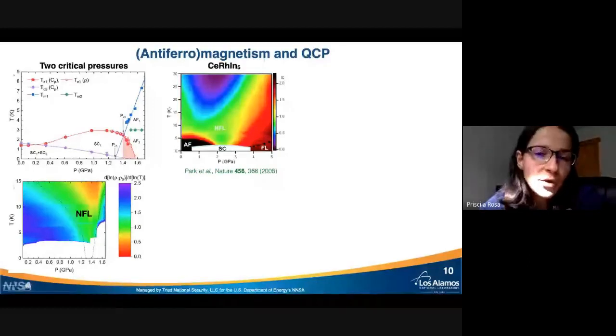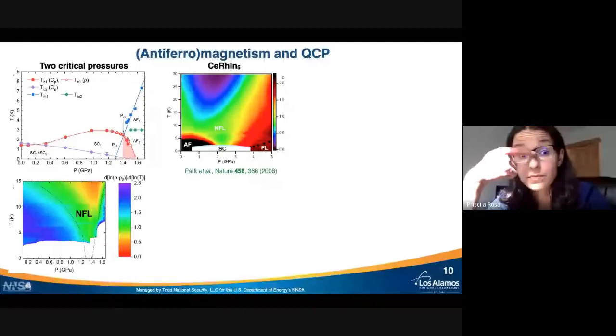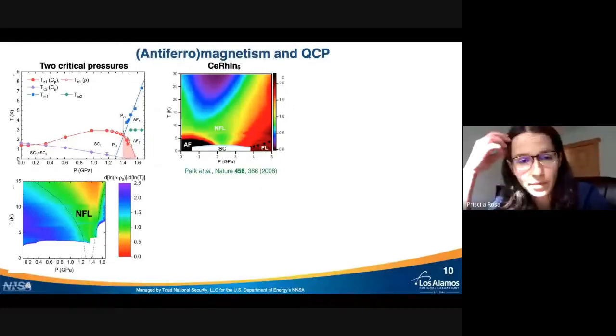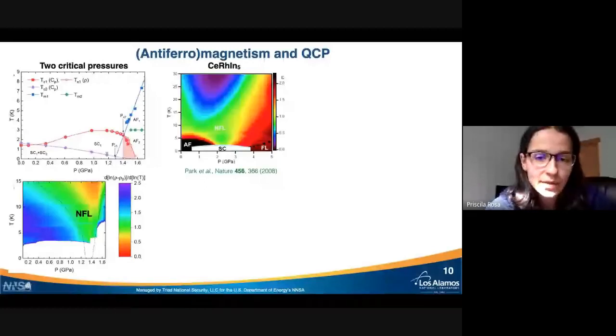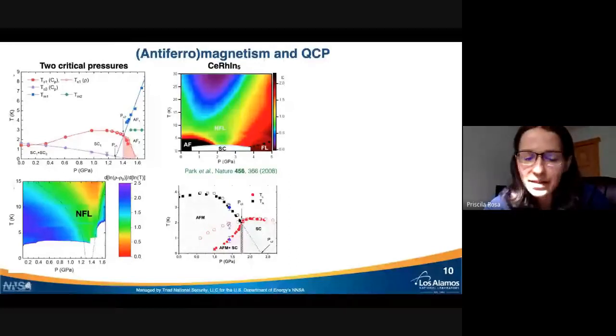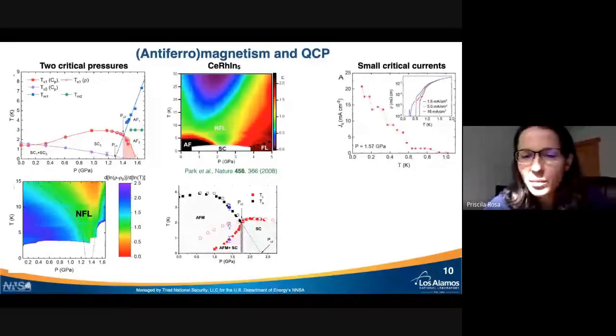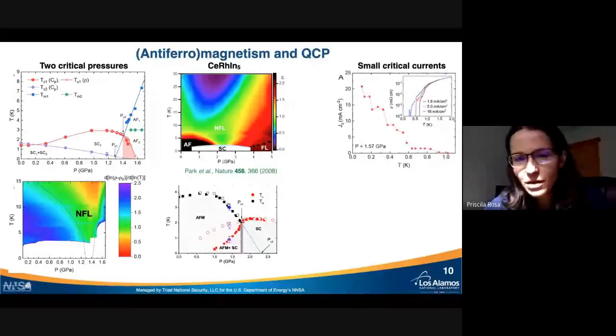And let me just point out that this particular type of non-Fermi liquid behavior has been seen before in antiferromagnetic systems, such as cerium rhodium indium five (CeRhIn5), and again, that resembles a quantum critical point. In that material too, it's so similar that we decided to investigate this coexistence region between antiferromagnetism and superconductivity. And I won't get into the details here, but the critical current is very small. It's not consistent with bulk superconductivity. So the two are coexisting, but not microscopically.